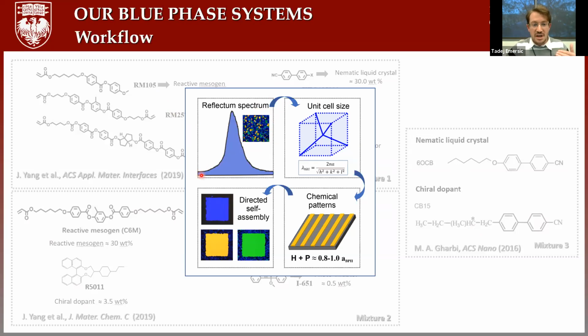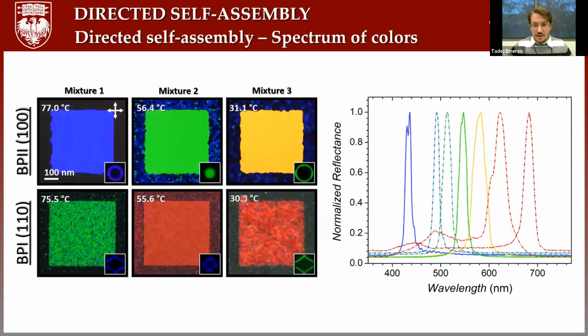So from this particular domain, we measure the reflection spectrum. We get the peak of the reflected light. And then according to the Bragg law, we can recalculate the unit cell size of this particular domain. Once we know this, we can use numerical simulations because they can help us reveal what the right parameters are, what the right dimensions of homeotropic and planar lines are to achieve the single crystals, right? And so we know that the best is when the sum of homeotropic and planar anchoring widths is pretty close to the unit cell size of the blue phase. So once we have this, then we inject the blue phase on top of these patterns, and the system should form the single crystals.